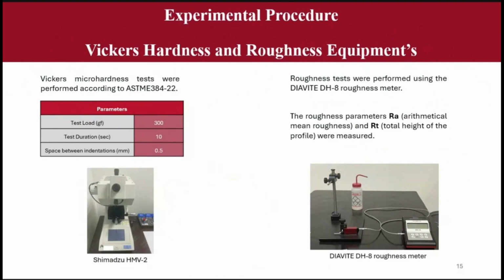We provide Vickers hardness and roughness testing. Here we can see the equipment for the Vickers hardness tests and for the roughness test, where we measure the arithmetical mean roughness and the total height of the profile.